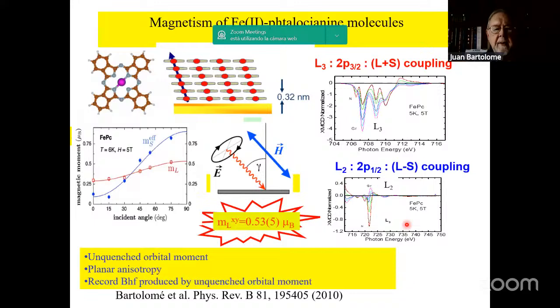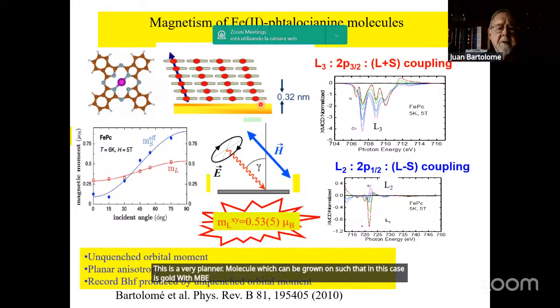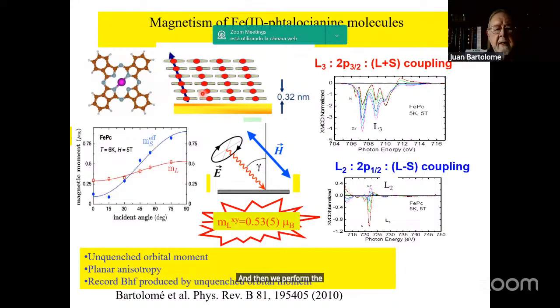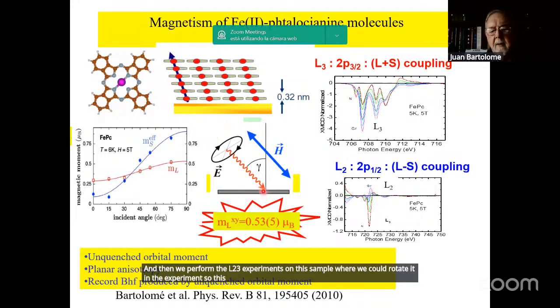Next case I want to show you is iron 2 in the phthalocyanine molecule. This is a very planar molecule which can be grown on a substrate, in this case gold, creating a pseudo crystal of molecules parallel to each other at a certain angle. And then we perform the L2,3 experiments on this sample where we could rotate it in the experiment. So this is the incoming light and parallel field at all instances.